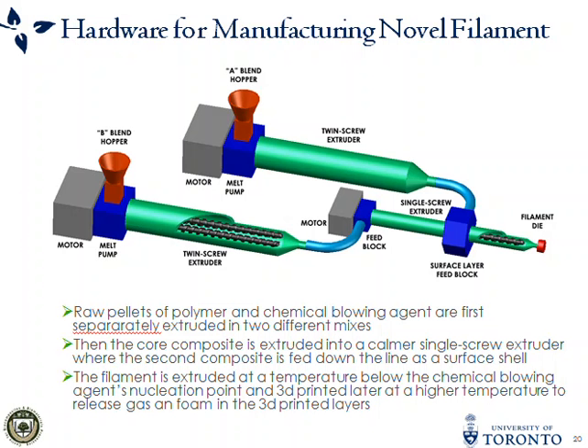Finally, where the shell and the core materials meet in the surface layer feed block, it creates the final cross section of the filament, and finally it comes out of the die in the form of a filament ready to be spooled for the printer. So the temperature we would use in the process of making the filament would be lower so that the chemical blowing agent doesn't get released. But then later when we 3D print, we would use a higher temperature and pinpoint that the gas will be released at that part of the process, and we get a 3D printed object.